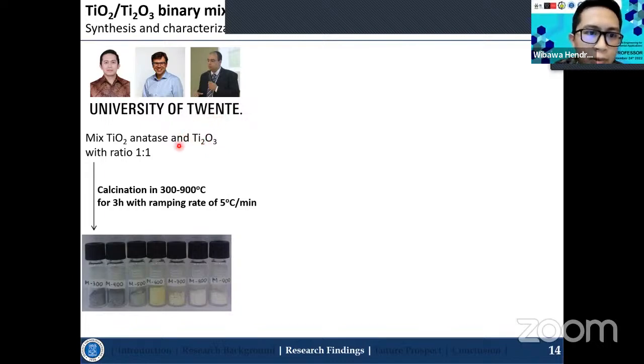So we try to mix it with the TiO2 anatase to create the titanium 3+ self-doped into the TiO2. The ratio of these two mixtures is actually 1:1, and I calcine at 300 until 900 degrees Celsius with the ramping rate of 5 degrees per minute for 3 hours.